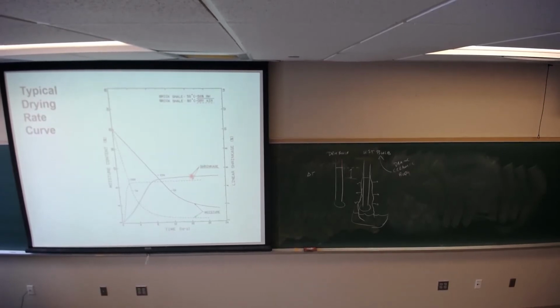If you go into the literature, there is a lot of literature that has to do with drying. Why is that if it's not the cause of cracking? Because that's where the cracks show up, and then everybody gets bent out of shape about that and decides, wow, we need to pay attention to the dryer, okay?